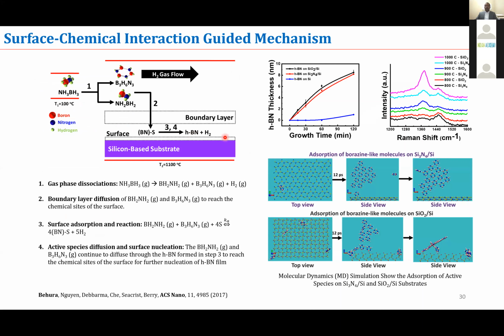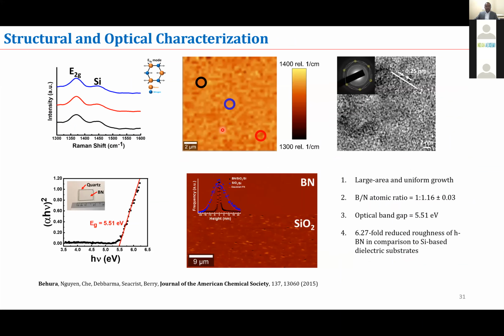And again, Raman spectra is called the fingerprint for all 2D materials research, and we took advantage of Raman spectroscopy to understand the boron nitride structure. For boron nitride, there is only one Raman peak, at about 1365 inverse centimeters, as you can see here. As the growth temperature goes up, the intensity of the boron nitride peak also becomes higher. That corresponds to a thicker boron nitride layer, because with higher temperature the growth rate also becomes higher. Therefore, you have more layers on silicon oxide substrates. These are some of the optical and spectroscopic characterizations of hexagonal boron nitride, which is a two-dimensional form of boron nitride, directly on silicon oxide.